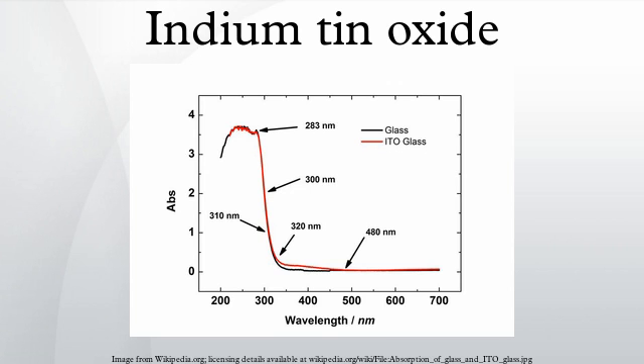The main concern about ITO is the cost. ITO can be priced several times more highly than aluminum zinc oxide (AZO). AZO is a common choice of transparent conducting oxide because of cost and relatively good optical transmission performance in the solar spectrum. However, ITO does consistently outperform AZO in almost every performance category including chemical resistance to moisture. ITO is not affected by moisture and can survive in a CIGS cell for 25-30 years on a rooftop. While the sputtering target or evaporative material used to deposit ITO is significantly more costly than AZO, the amount of material placed on each cell is quite small, so the cost penalty per cell is quite small too.